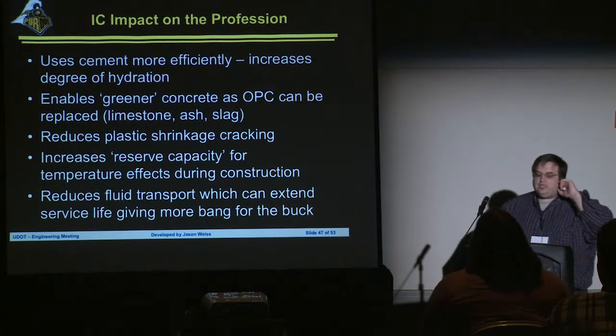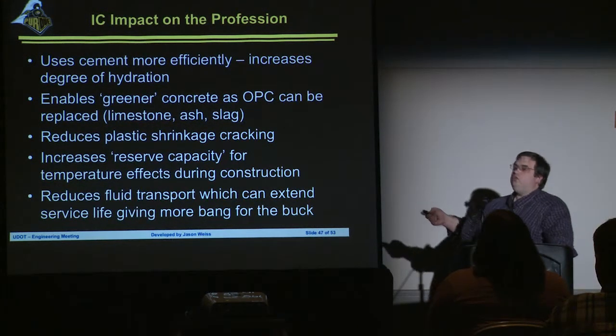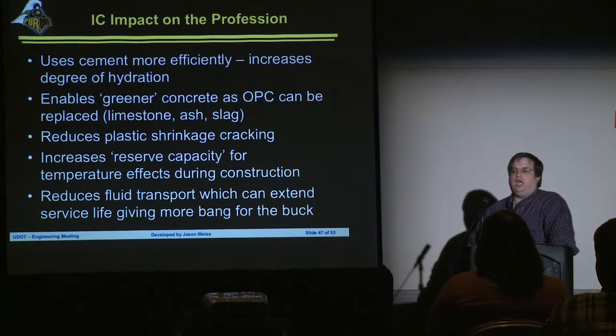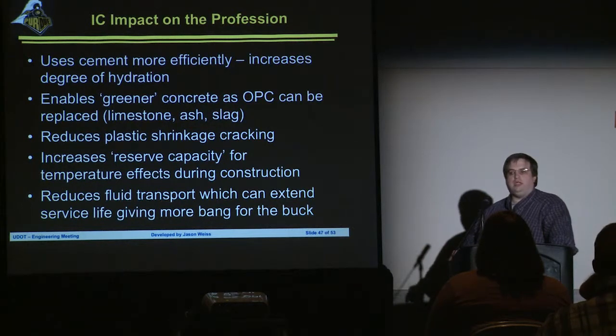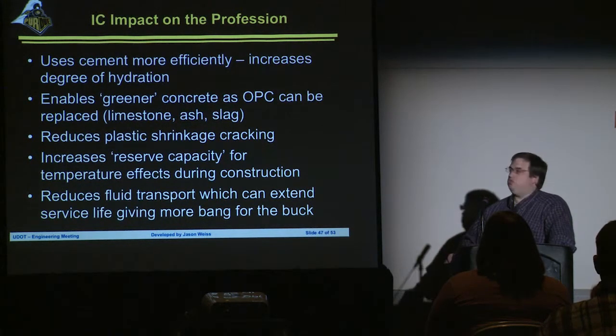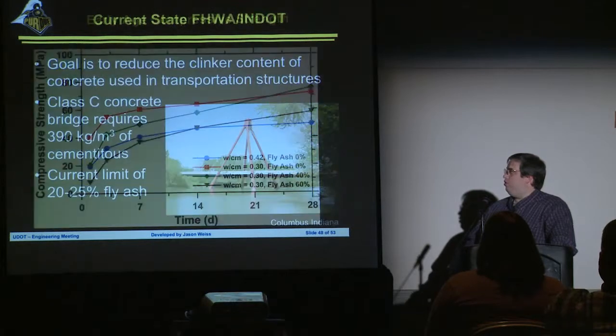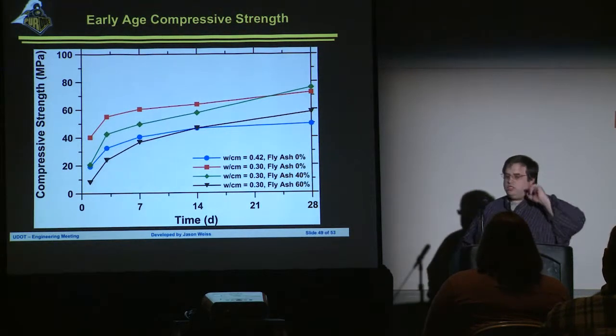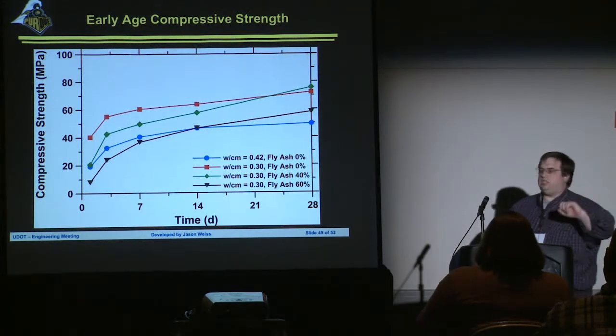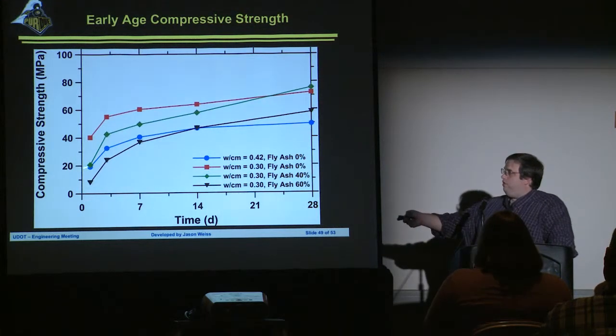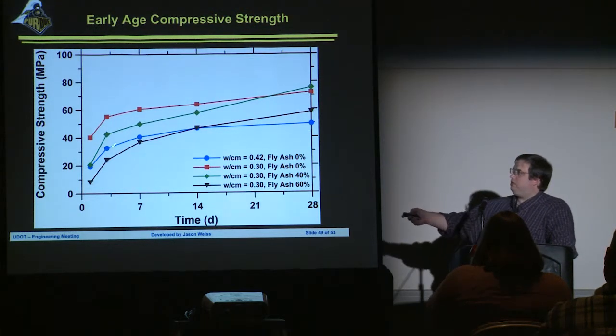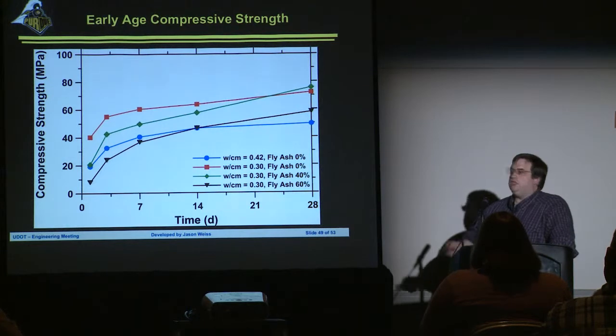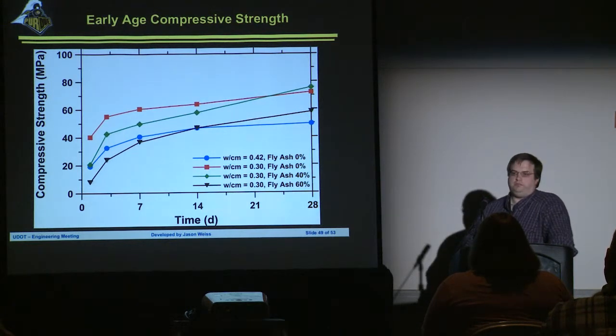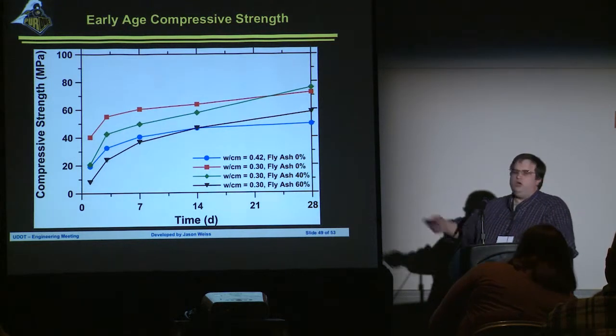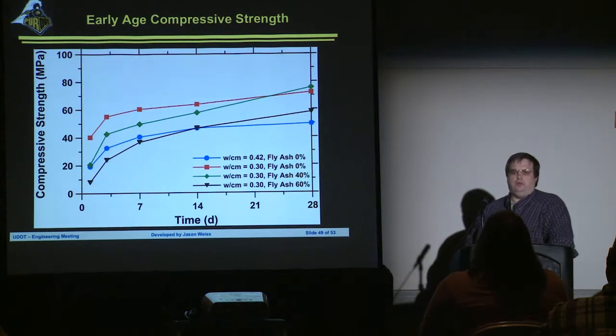In addition, though, this has some other big benefits. We can use our cement more efficiently because all of a sudden now we can hydrate more of that cement. So as we grow to greener and greener cements, Portland limestone cements, we start to use more supplemental materials, we've got some real big benefits in here. So what I want to do is mention a project that we've been working on recently for the Federal Highway Administration where we've essentially said let's take a conventional mix and let's find out what happens if we reduce the water to cement ratio. We reduce the water to cement ratio, we increase the compressive strength, nothing real magical.